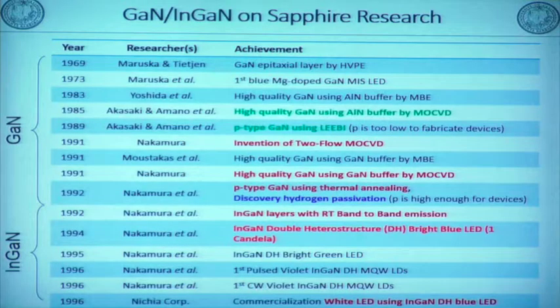Also, in my case, the most important invention is the indium gallium nitride emitting layer, or active layer, in '92. N-type layers are available, and also the buffer layer. Professor Akasaki and Amano invented the aluminum nitride buffer layer in '85 to improve the crystal quality of gallium nitride. In my case, I invented the gallium nitride buffer layer in '91. So that's the contribution.